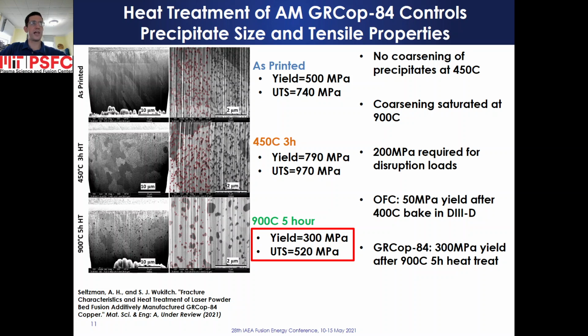GRCop-84 in as-printed condition without any heat treatment has a yield strength of 500 megapascals and an ultimate tensile strength of 740 megapascals. A 3-hour, 450 Celsius heat treatment increases yield strength to 790 megapascals and ultimate tensile strength to 970 megapascals with no observable coarsening of precipitates.